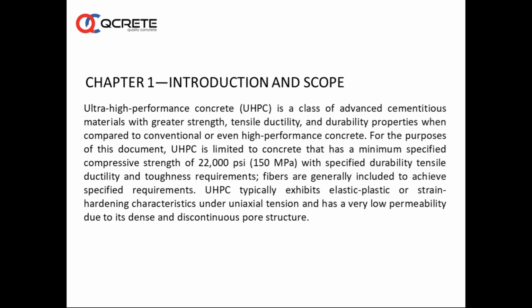This ultra high performance is the next level where very high strengths are gained in concrete. Also, very high performances are expected of the concrete. UHPC typically exhibits elastic plastic or strain hardening characteristics under uniaxial tension and has a very low permeability and discontinuous pore structure. This is one of the important characterizations of ultra high performance concrete. It has almost negligible permeability.